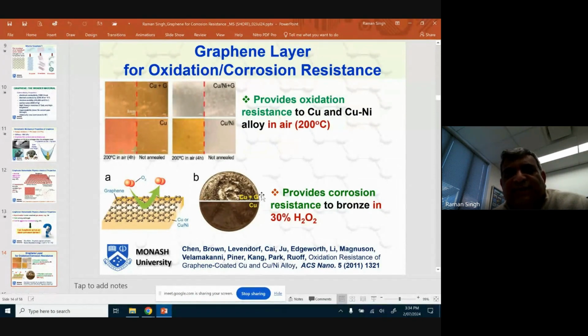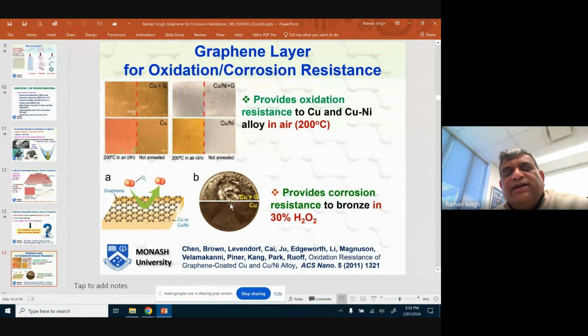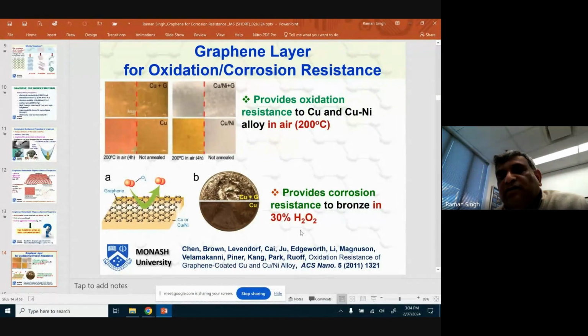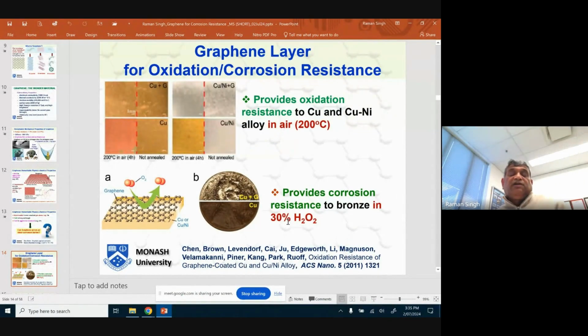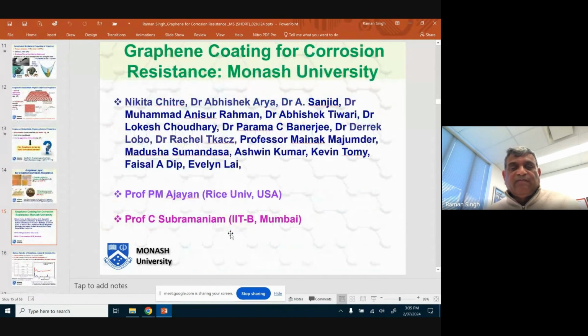They did another experiment. That was, they took a penny and they coated the upper half of the penny with graphene, and lower half was left uncoated. And they exposed the entire penny to a highly oxidizing hydrogen peroxide solution, and you can see upper half, which was coated with graphene, did not tarnish at all. It did not corrode at all, whereas lower half underwent corrosion.